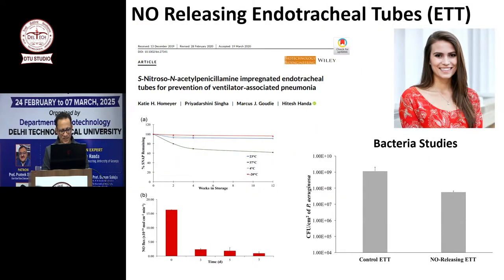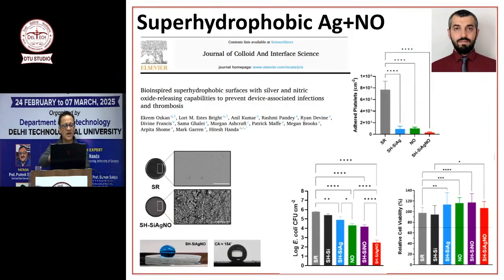Then, this study is, so Ekrem was a postdoc in our lab and he did a lot of good work. He did his PhD at University College London and he was very good at making super hydrophobic surfaces. So this work, like you can imagine, see the contact angle is 154 degrees on his surfaces. This is a silicone rubber and after he adds his coating to it, it makes the surface super hydrophobic. And he also made this surface silver and nitric oxide releasing both.